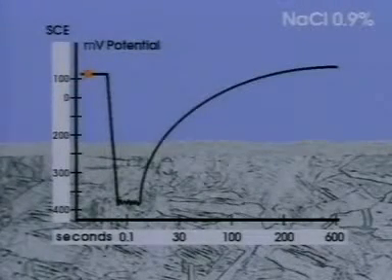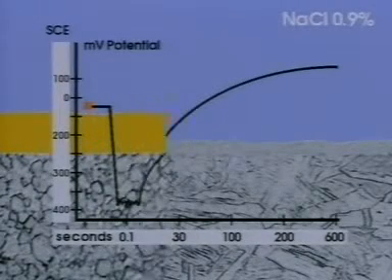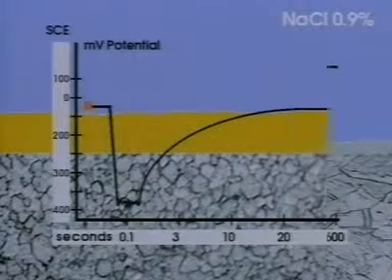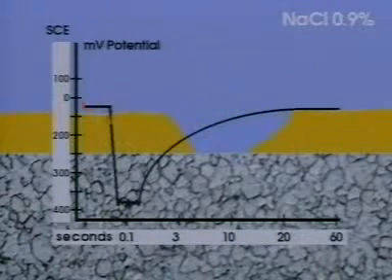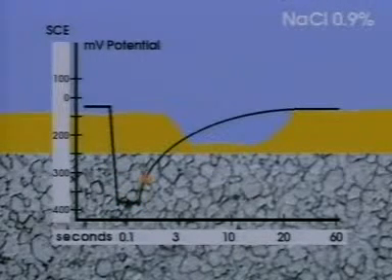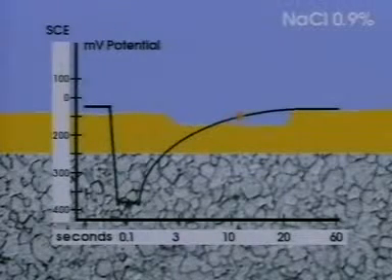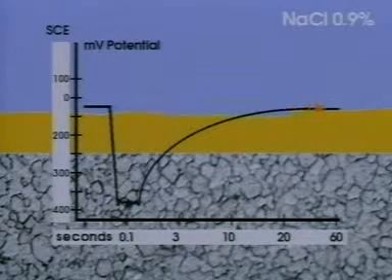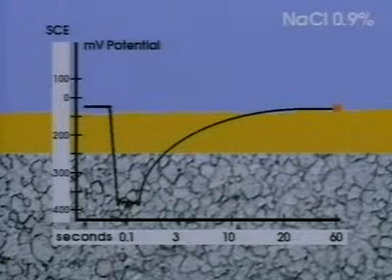When we compare the curves of stainless steel and titanium, we notice that the shape of the curves are similar, but that the time scales are quite different. Titanium repassivates much faster than chromium because it is much more efficient in obtaining its oxygen for the passive film directly from water molecules, whereas the chromium in steel prefers to use the rare dissolved oxygen molecules.